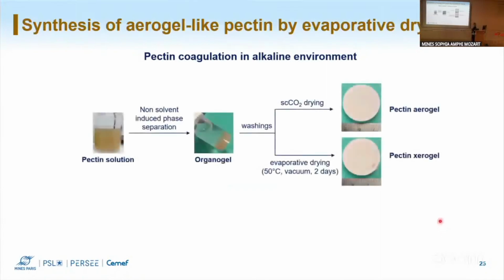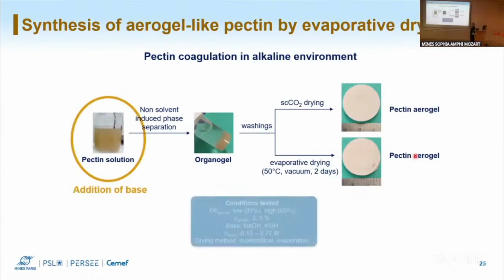In order to avoid supercritical drying, we tried to do pectin coagulation in alkaline environments. So now the scheme changes a bit: there is a new leg here, adding evaporative drying in order to receive xerogel materials. When I say xerogels, I always refer to materials dried by evaporation, and aerogels by supercritical drying. We worked on the pectin solution and we added base, and we used both high and low methoxypectin. We worked with different concentrations of pectin, 2 different bases, and different concentrations of base, and we saw how the drying method affects the material properties.